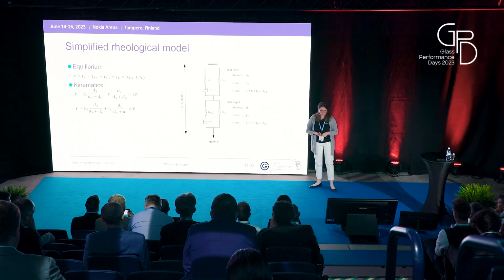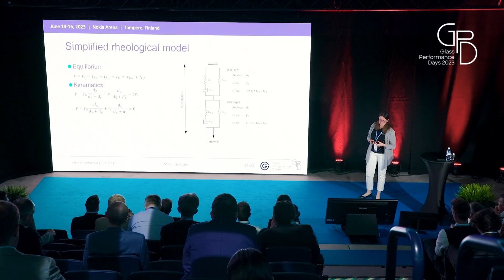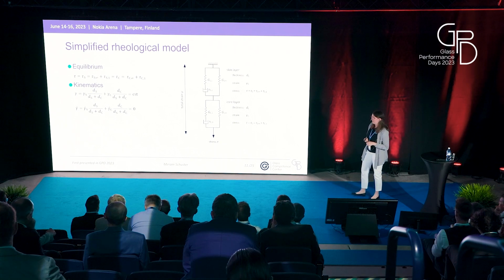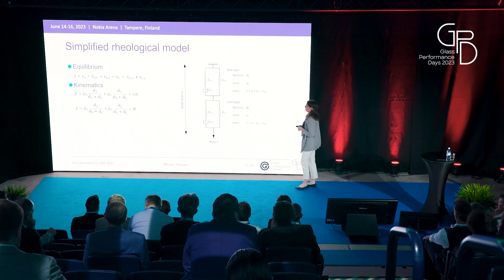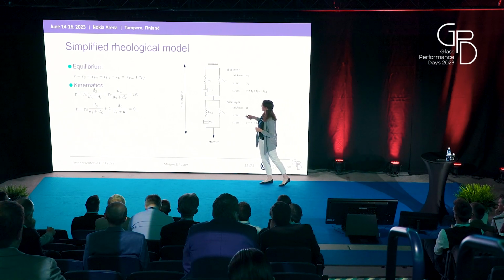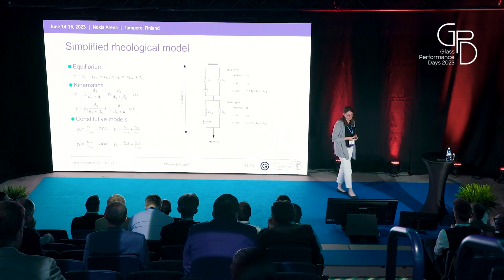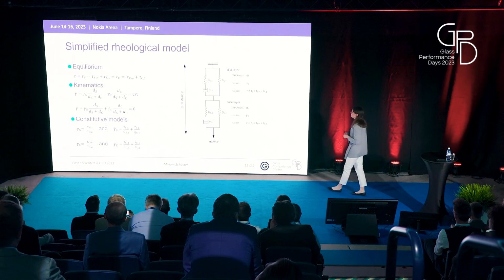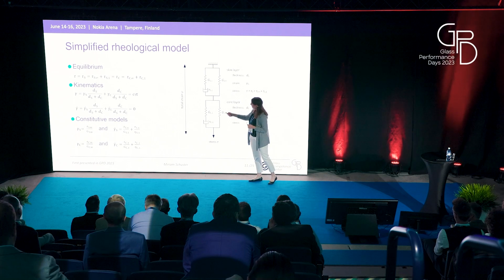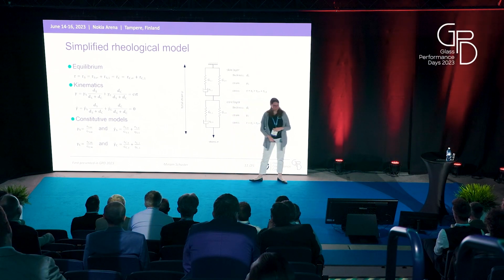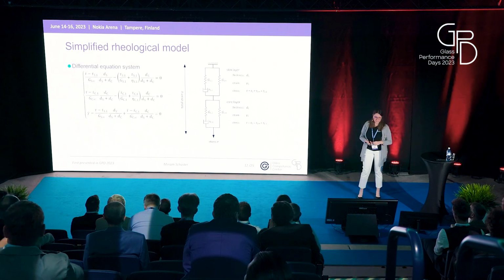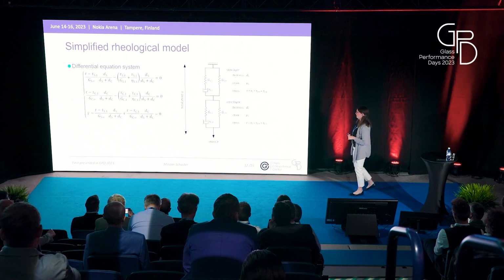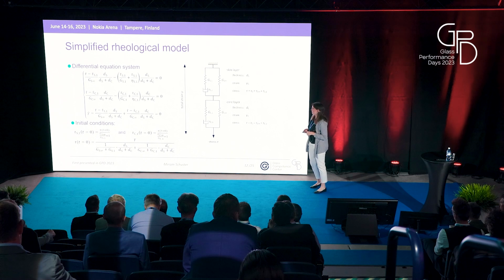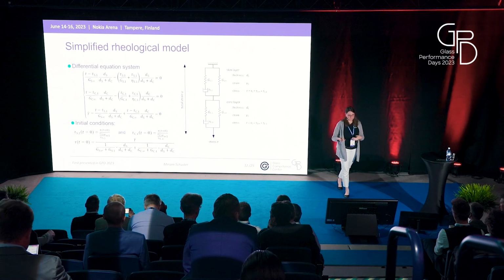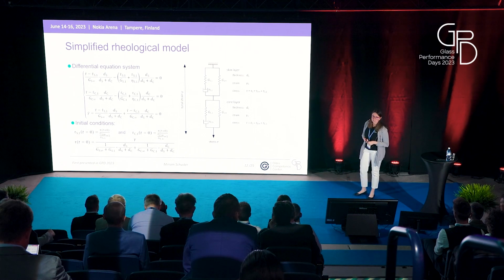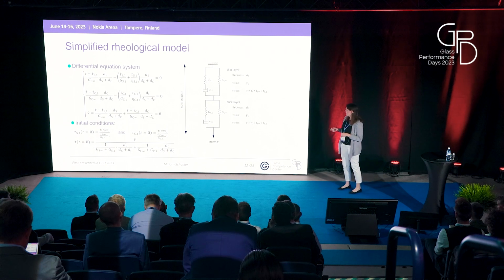Second thing is the kinematics. It's a relaxation test, which means that the total strain remains constant, and hence the strain rate equals 0. And the total strain can be calculated from the strain of both layers. And next, I consider the constitutive models for the elastic springs and for the generalized Maxwell models. And by combining all those equations, we obtain a system of differential equations. I don't want to go into detail for that, but when looking at some initial conditions, which mean the conditions at the time equals 0, then we can solve this differential equation system, for example, analytically or numerically, and obtain